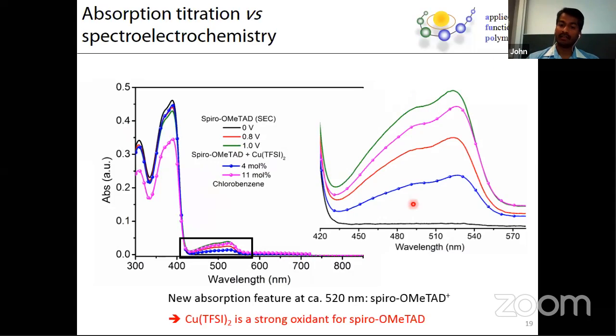So you can clearly see that the black, red, and green curves are from spectroelectrochemistry. With increasing potential, so while we apply more and more potential, basically we electrochemically oxidize the system. Now we compare these curves with chemically oxidized systems.